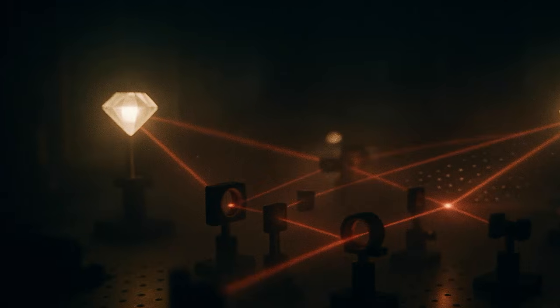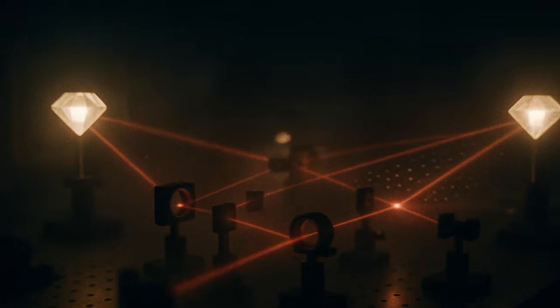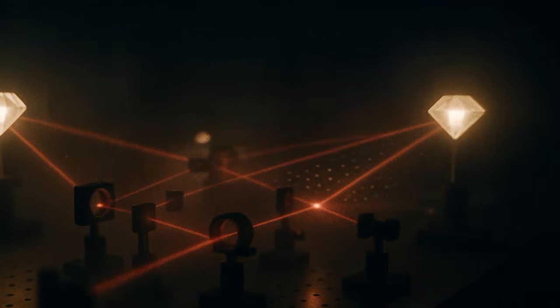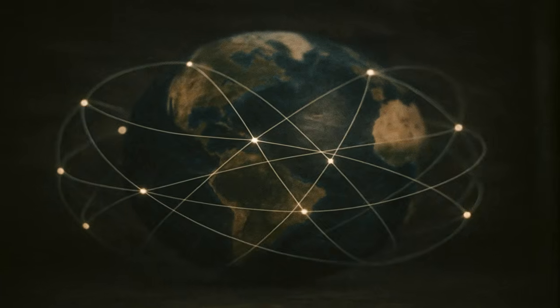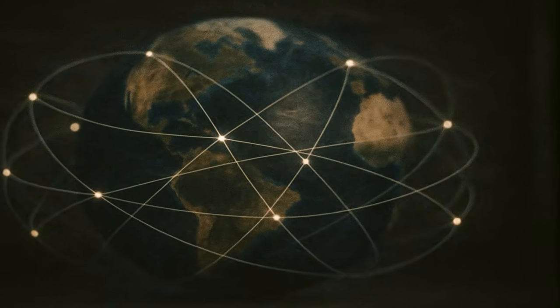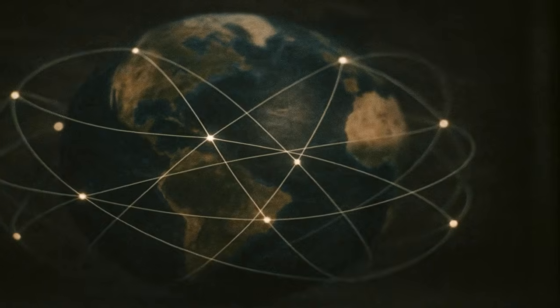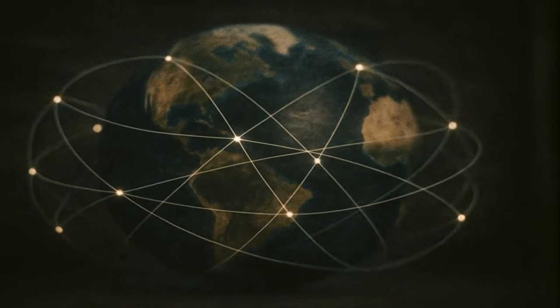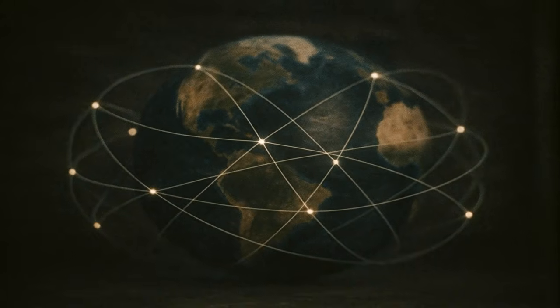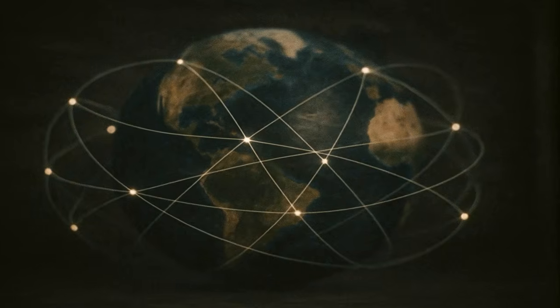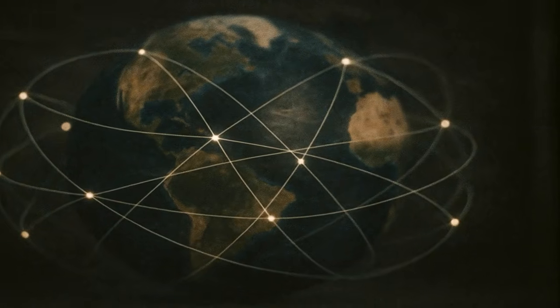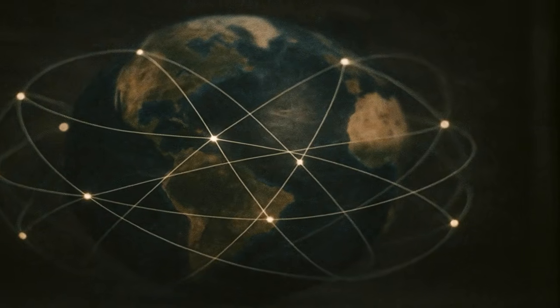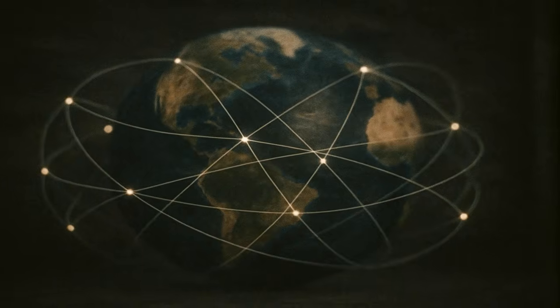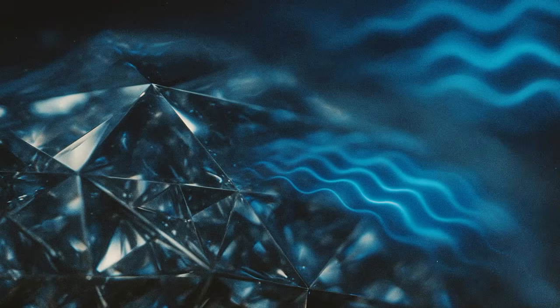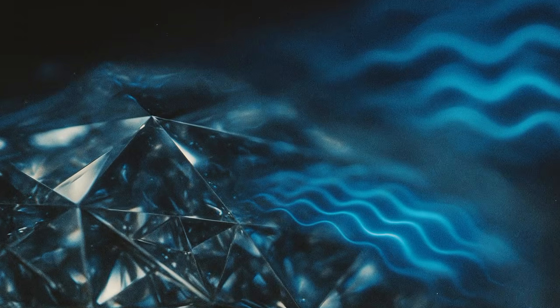The quantum yield of 70 to 80% comes from the rate competition. Radiative decay, rate 1 over 13 nanoseconds, equals 77 megahertz. Non-radiative decay rate includes intersystem crossing to the singlet manifold. That singlet state lives about 250 nanoseconds. The singlet can decay back to the triplet ground state or emit a phonon and drop to a lower singlet level before crossing back. The whole process adds a non-radiative pathway. But it's slow compared to the direct radiative decay, so most photons come out, 70 to 80%.